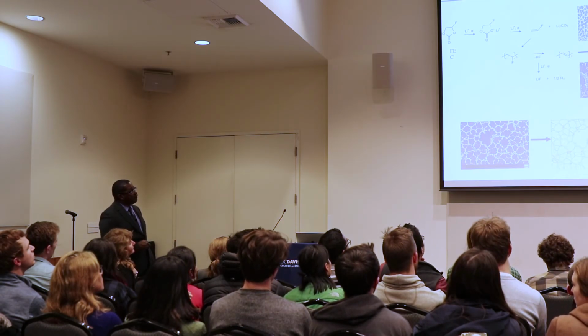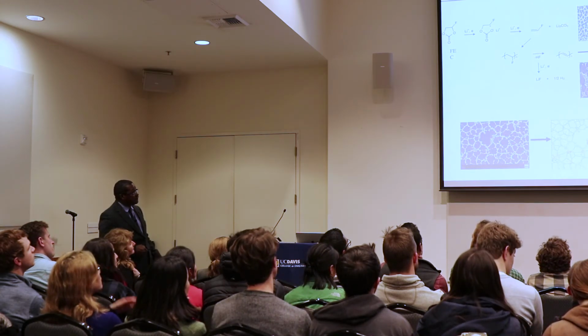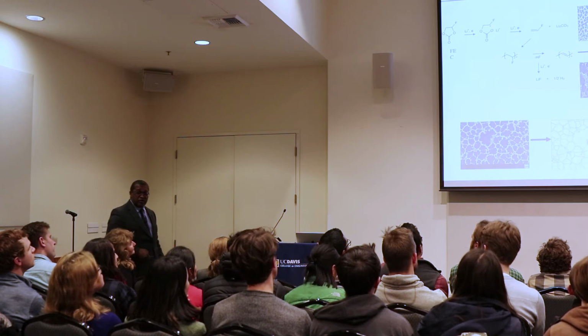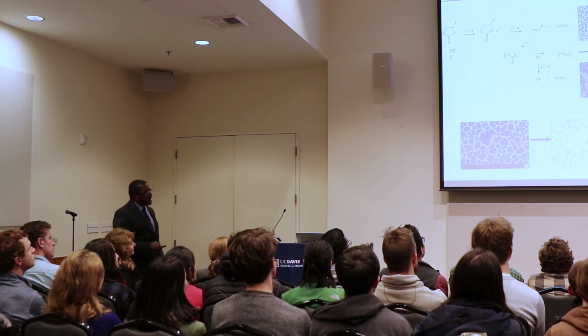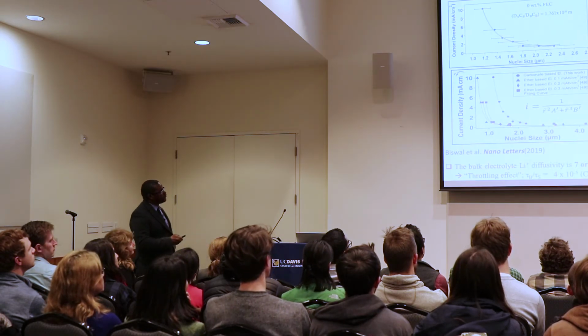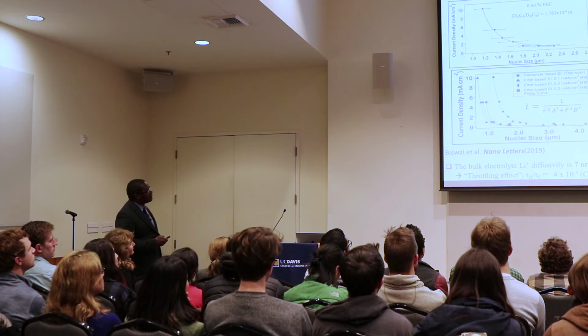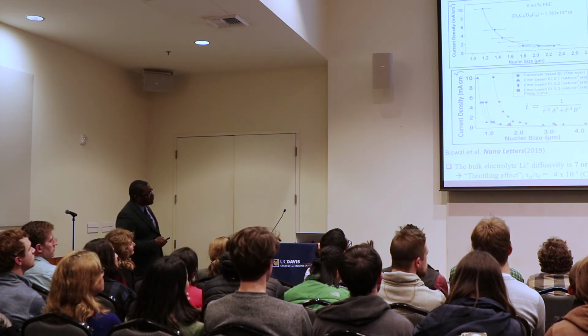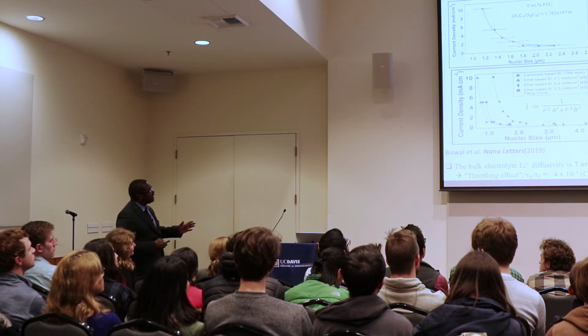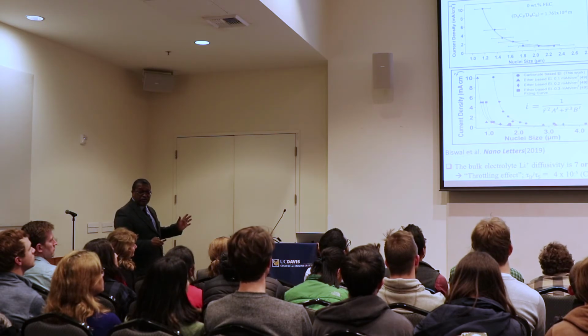We measure the bumps, or nucleate size, at that minimum point for different current densities. We fitted them using ImageJ, getting things like the average size of the bump and the standard deviation. We then fit the results to the model, and this is what you get. Large error bars because we're averaging over many bumps, but the fit is actually reasonably good.